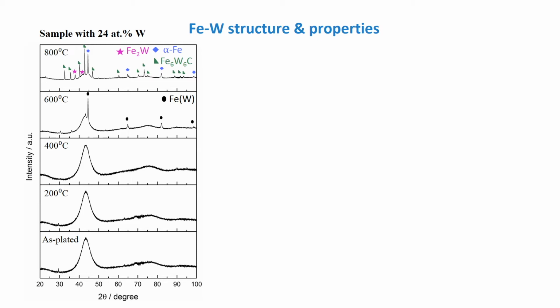The thermal stability of the coatings, together with the heat treatment effects on the mechanical properties of the iron tungsten coatings, has also been studied. Here I include the results from the coating with 24 atomic percent of tungsten. The sample retained its amorphous structure up to 600 degrees, where a partially crystallized structure is observed. At 800 degrees, we observe the formation of different crystalline stable phases, but the material is still not fully crystalline, as shown by the broad shoulder visible in the XRD spectra.